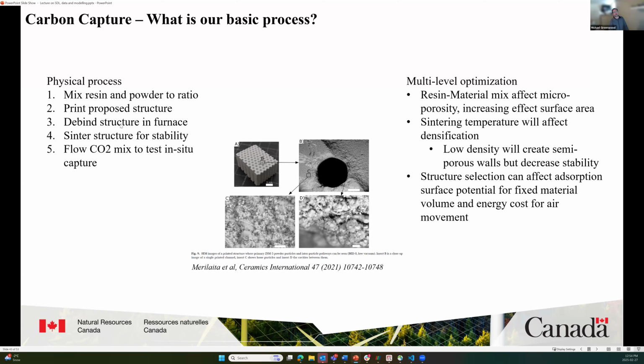We take the print cell out, we debind it in a furnace. So basically this is raising it to a temperature where we burn off all of the resin. The structure then needs to still be self-sustaining. That's where if you get lower than 20%, it will just collapse. Then we sinter it. We raise the temperature to between, say, 1,000 to 1,200 degrees Celsius. The sintering process structurally binds the zeolite. Then we take the cell out and we flow CO2 through it to measure the in situ capture.